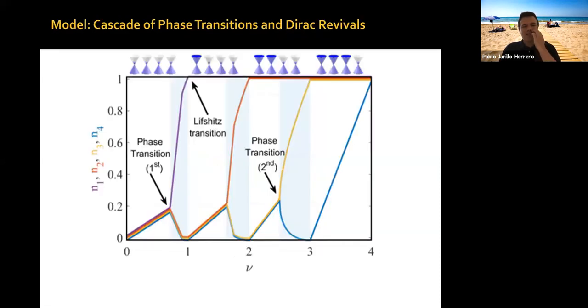So the simplest model that we could come up with, and it's, again, zeroth or first order, and a lot of people are now doing theory to better understand the features that are present in this model, is the following. There is a cascade of phase transitions and so-called Dirac revivals, we call it, in the evolution of the system as a function of filling. So let's start from charge neutrality. You know that you have these four flavors, spin and valley, in magic angle graphene.